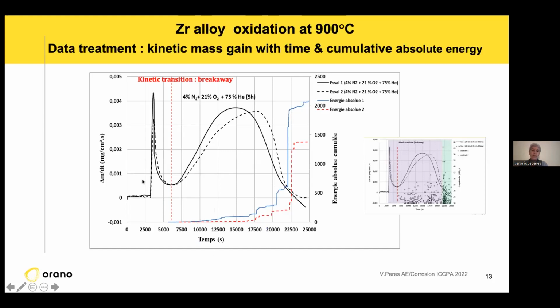And you can see here a representation of the kinetic mass gain. You have a first parabolic increase, the transition, and then again an increase of the mass gain. And you can see that the noise only comes after the breakaway, since we have to have cracks to make the noise. After the breakaway, we have a first domain where you can see the increase of the noise in the samples, and then during the cooling, which is in green here, you have a lot of noise due to cracks. In this case, it's the first time we have identified cracks during the heating, the corrosion, and cracks during the cooling.